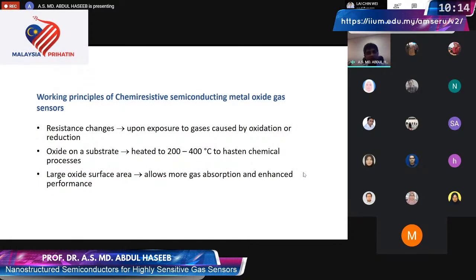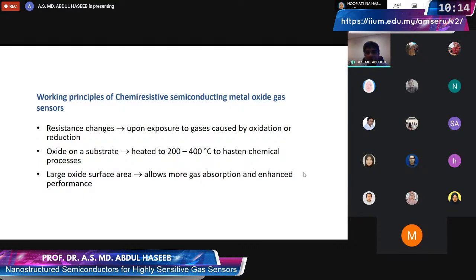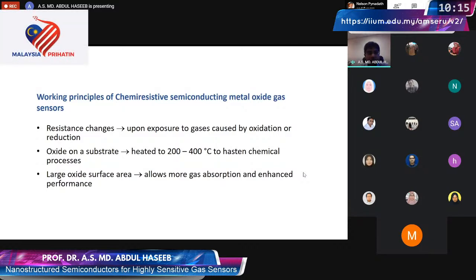The working principle, as I mentioned already, is chemi-resistive in nature. That means that when you expose the sensing material, the active material, to a certain gas, then a redox reaction happens on the surface of that material. So oxidation and reduction happen, and as a result, charge carriers are transferred and generated. And because of that, the resistance changes. And we measure the resistance as a function of the concentration of the gas. And from there, we can detect the gas and its concentration in a particular system. Normally, we use a slightly elevated temperature to do the detection in an effective and efficient way. And these gas sensors are produced in a way which exposes larger surface area because all the reactions happen on the surface.